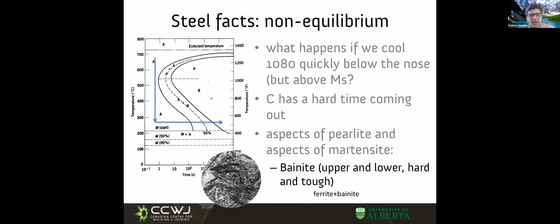What do you think—is this a fine microstructure or a coarse microstructure? Guesses. Fine or coarse? Fine, very fine microstructure. And in addition to being fine, it's finer than pearlite, and also has some mixed aspects, some sort of hybrid with martensite, because in addition to this small amount of diffusion making these fine structures, we have some amount of displacement of the lattice.